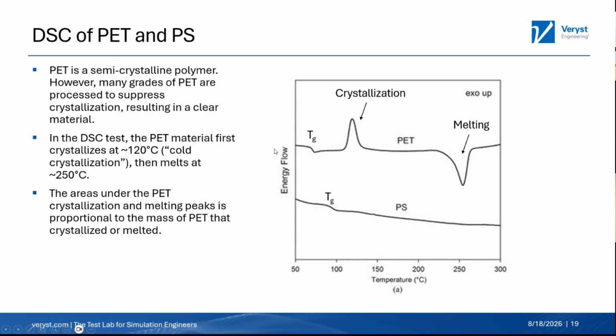to take one step back, that clear PET that is most commonly used for thermoforming applications, because it's clear, you can see through it, it makes a nice packaging material, is processed so that it's fully amorphous. So even though PET intrinsically wants to form crystalline domains, if you quench it, if you cool it really fast from a melt processing step, you can prevent the nucleation and growth of those crystalline domains and maintain that clarity. So what happens is we heat the PET up, it goes through Tg, it's much, much softer.